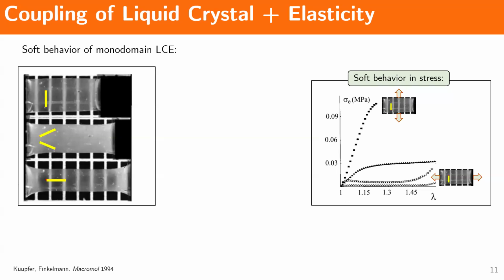And so I'm going to talk about the interesting behavior of these liquid crystal elastomers that people have seen. And in particular, we see that these materials have this spontaneous stretch, right, that happens. And this really stems from the coupling between the liquid crystal or the mesogens that we see and the rubber elasticity. And in particular, if we look at the mechanical behavior of these materials, okay, they're undergoing this large stretch under very low stress, right? So this is the interesting behavior, which is also called the soft behavior in these materials. And this really comes from the fact that the mesogens can rotate and orient towards a particular preferential direction. And that direction is not fixed, and it can usually be influenced by external factor. In this case, would be the external loading direction.